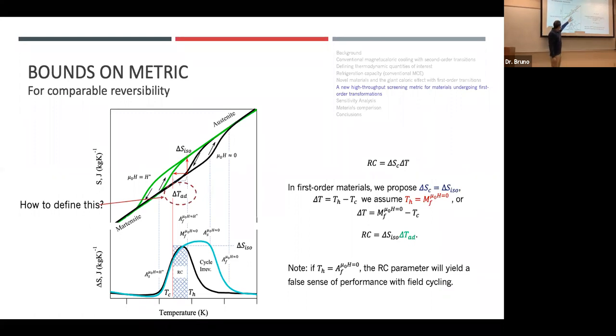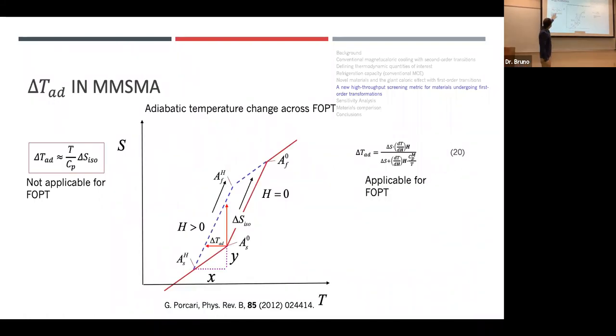So this parameter, delta T adiabatic, is very important, and we need to be able to define that as well. Before, we defined it using our dS equation, our entropy, right? But this, again, is not applicable for a solid-to-solid phase transformation. It's only applicable for a single-phase ferromagnetic material across a second-order transition.